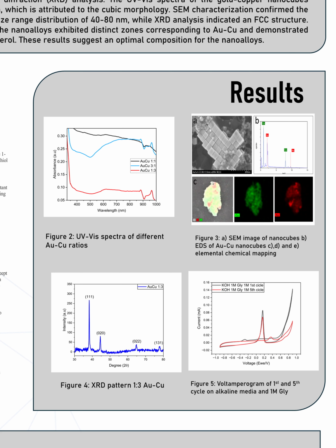The UV-Vis spectrogram displays the absorption bands of both gold and copper at the same time. The characteristics of these bands are influenced by the relative presence of each component. For instance, in a 3:1 ratio, the 523 nanometer peak, which corresponds to gold, significantly broadens, while the peaks near 800, 870 and 990 nanometers are characteristic absorption peaks of copper. In a 1:1 ratio, both bands experience a decrease in intensity. Finally, in a 1:3 ratio, the absorption peaks of copper are more intense than the gold peak.